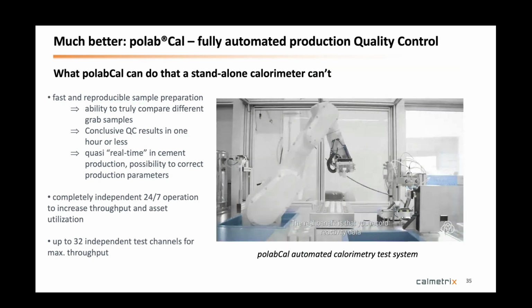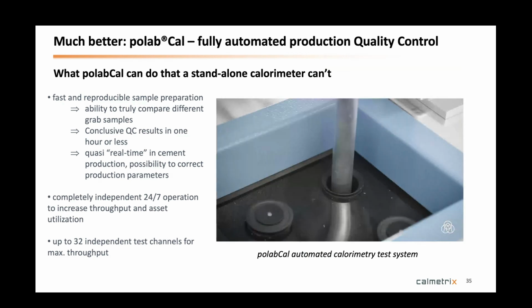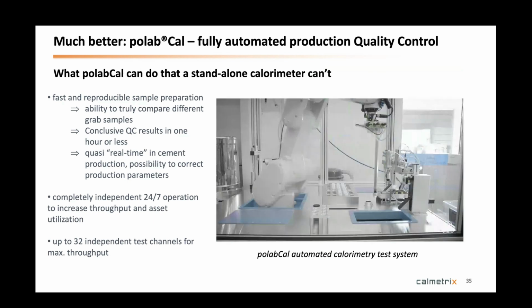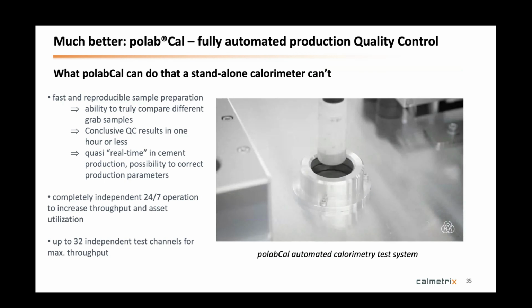For a cement production plant, it's actually interesting because it's quasi real time. In 30 minutes, you would see if something is affected, and you would still be able to make changes in production that are meaningful. Because otherwise, if you do the changes in production tomorrow, you have already produced a bunch of cement that's stored somewhere and that wasn't necessarily very consistent. But this particular one here just helps you to do this in the best possible way.